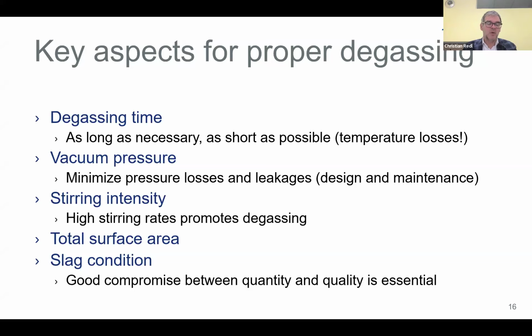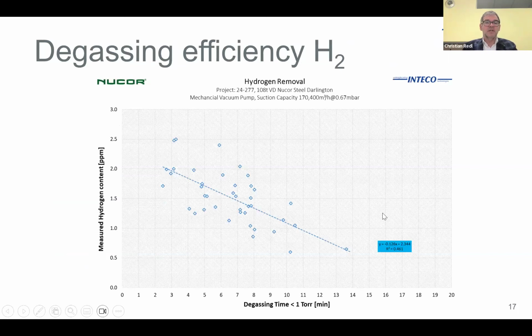So this is on the one side also dependent on the height to diameter ratio of your ladle, and then in the end also dictated by the slag, which surface area can be exposed to vacuum to have this good degassing efficiency. The slag condition is, of course, also always a compromise between quantity and quality, and this must be decided from case to case for each heat and steel grade.